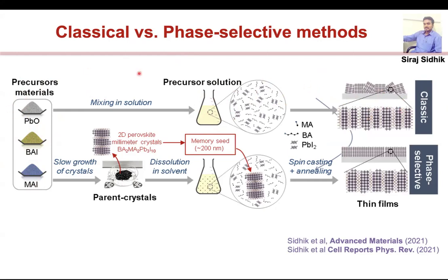But instead of doing this, what we did was we take these materials and first make these single crystals, the ones I showed you, which had these very nice resonances. So we can control that n number very well. And we made these types of crystals, and we take those crystals and then dissolve them into the solvent that we want. Okay. So compared to what has been done, we take these pre-made crystals, just one extra step. You can make these in large quantities, you dissolve them in there, and then we cast a film.